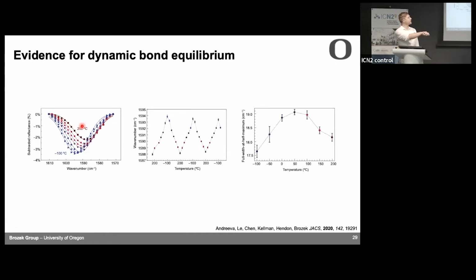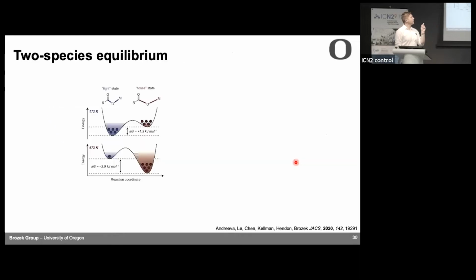The other thing that was unexpected is that the width of the peak gets biggest at an intermediate temperature. I sort of naively thought that you keep heating it, it's just going to keep getting broader, more disordered. But it's actually widest at an intermediate temperature. So that wasn't clear to me why, but it turns out that's really important. The way we started to understand this is we view this as an equilibrium between the bound states and the unbound states. And so you can think about this as this cartoon potential energy surface here. At low temperatures, you favor more of the tight states, and at high temperature, you favor more of these loose states.